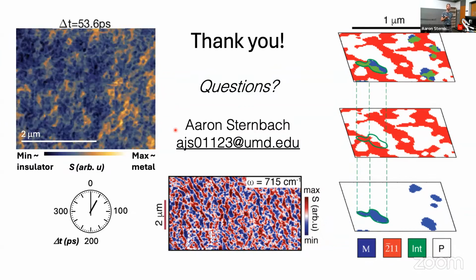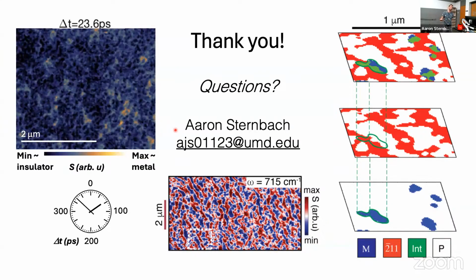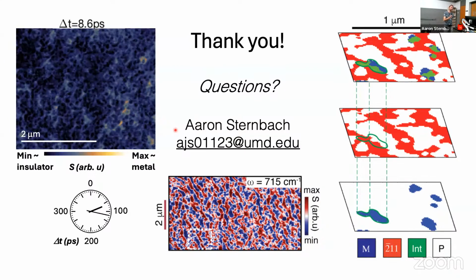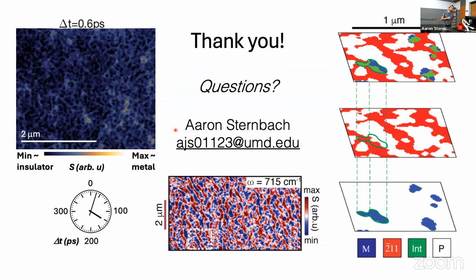This is around 60 femtoseconds. So there's a lot of changes that occur in the structure on timescales after 60 femtoseconds. In those first 60 femtoseconds, there's a lot of data on this regime. You can't see the conductance do anything interesting in that range.